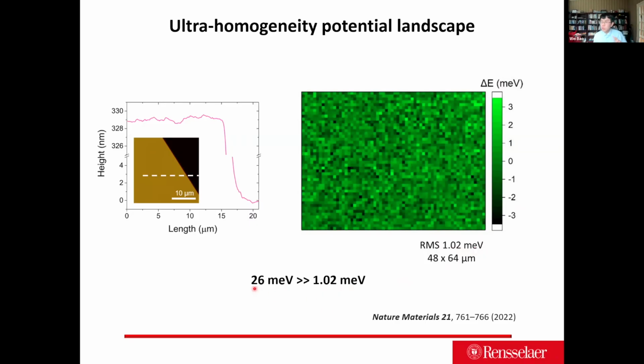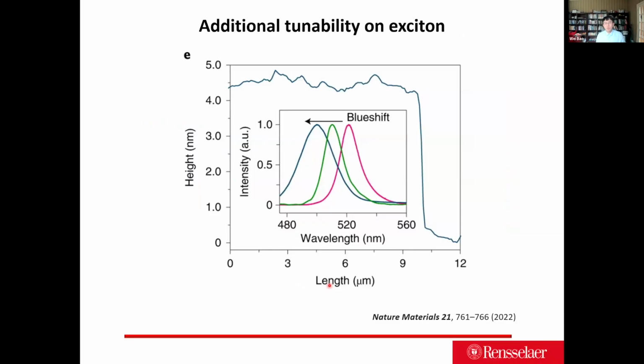Compared with the room temperature thermal fluctuation, whose RMS value is 26 meV, our sample only has an RMS roughness of about 1 milli-electron volt. So compared with the thermal fluctuation, our sample is really flat. You don't see any variation locally. This also can introduce additional tunability on the exciton.